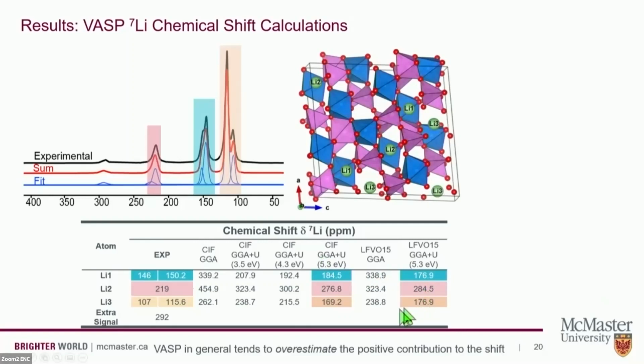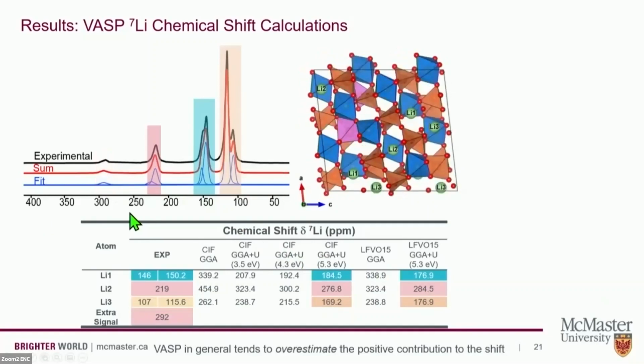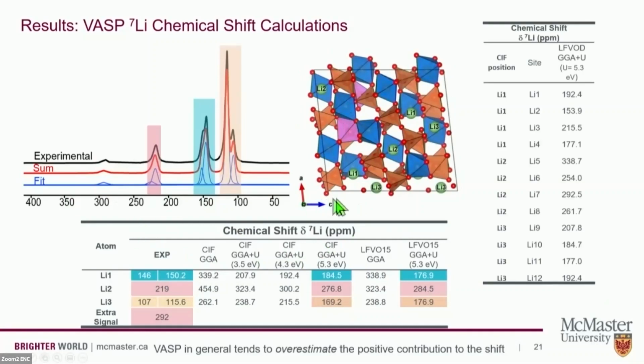But Tiana had noted, and I said, don't worry about it, it's a small feature, but she was always bothered by this chemical shift up about 300 ppm. And so we finally got a bit of understanding of what's going on here when we did the step of mixing the structure, so giving 1/8 of the asymmetric unit cell to this new vanadium position and the rest in the original. And that mixing of those two positions, which we think is what happens in the experimentally prepared samples, suddenly generates a chemical shift.